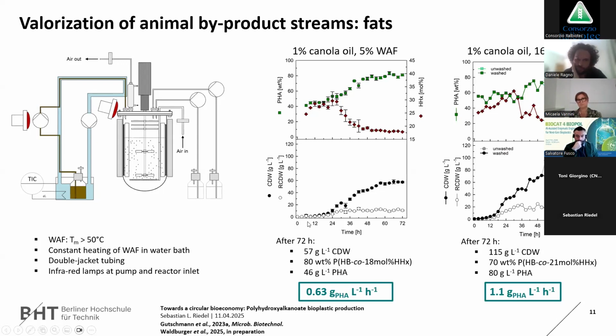What we also measure, here you see the circles which are open. So this is the biomass without PHA, and the total biomass, and when you subtract it, you can measure the PHA in gram per liter, and here we always see our HHX content.